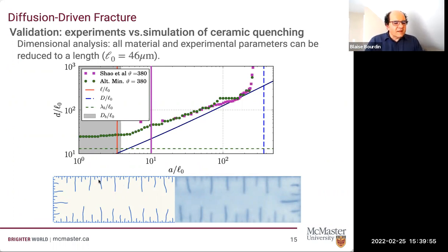And the way you can quantify the difference between these, or the geometry of the crack pattern, is by drawing a line at a fixed distance of the free edge and counting the cracks that intersect this line. So that gives you crack spacing as a function of the distance to the exposed edge. So this would be the distance from the free edge. This would be the crack spacing. It's normalized in some form. The purple squares are the measurements by a group at the Chinese Academy of Science in Beijing. And the green dots are our numerical simulation. So again, complicated problem, lots of cracks growing, nucleation of cracks, but we get a very, very good approximation.